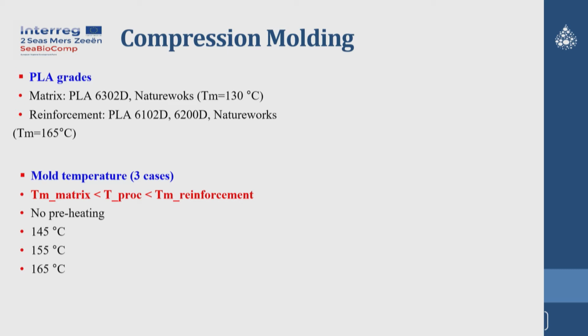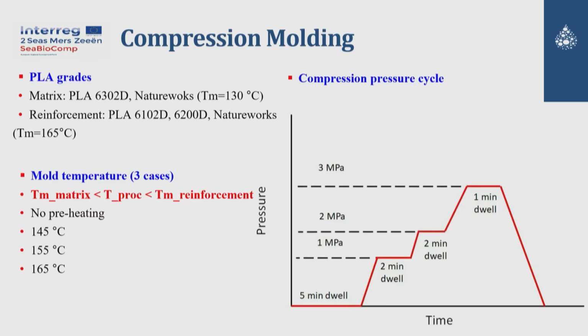Moreover, what was interesting in this project was that for all these preforms we didn't need preheating and pre-drying. So manufacturing is relatively easy because we didn't need any pre-treatment of the material. Then, in terms of the compression pressure, we adopted a kind of staged compaction. That means we started from a low pressure and increased the compression pressure sequentially, because in compression molding one of the common problems is excessive lateral squeeze flow, and we can lose a large amount of matrix material. Anyhow, when we tested the conventional compaction cycle with constant pressure, it works also.